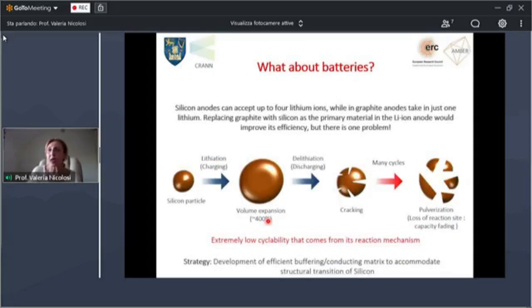We've also used these materials in battery technology, and we decided to start from an anode material, silicon, that has been a very highly recommended and suggested material in the battery field for quite some time, at least 10 years. Silicon is very good because it can accept up to 4 lithium ions as opposed to 1 that currently graphite anodes can take. So it has a very high theoretical capacity.